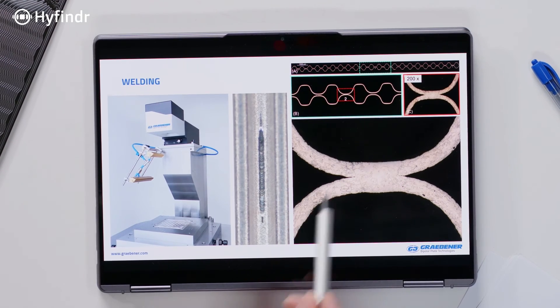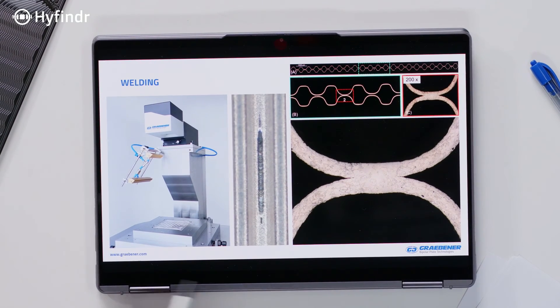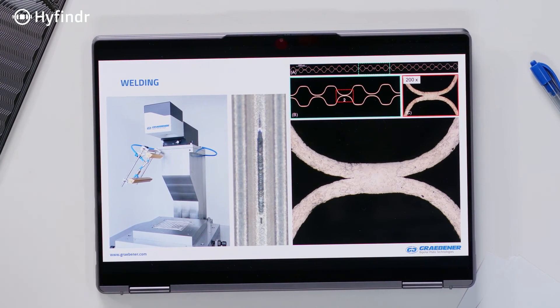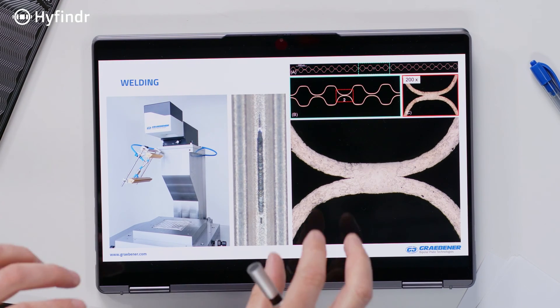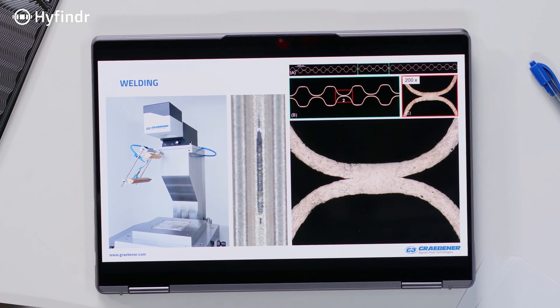It's not only about knowing how to adjust the laser — how much power you need — it's really a big part of the knowledge: how you do the fixation, how you do the clamping, so that you have a good situation for the welding process itself. Also, the quality of the forming is very important to get a stable welding process.